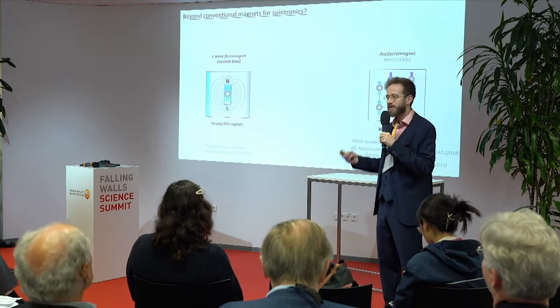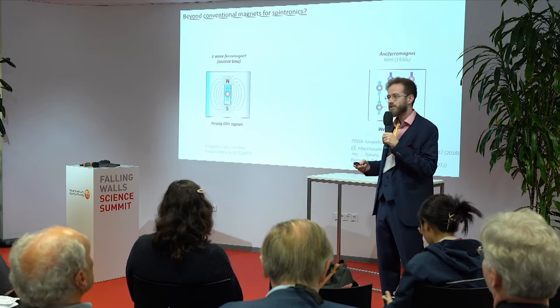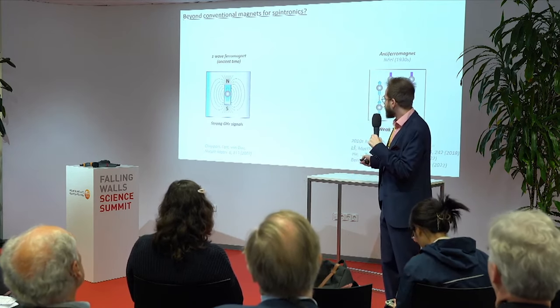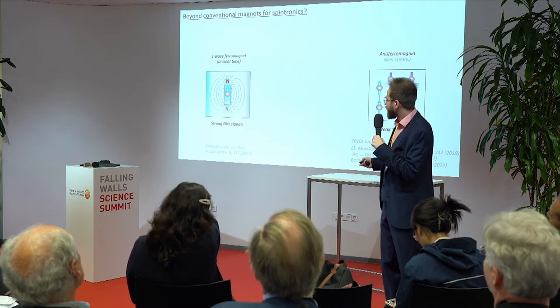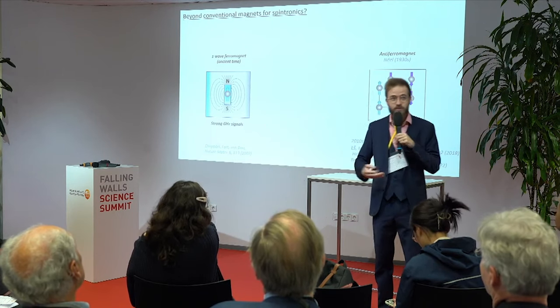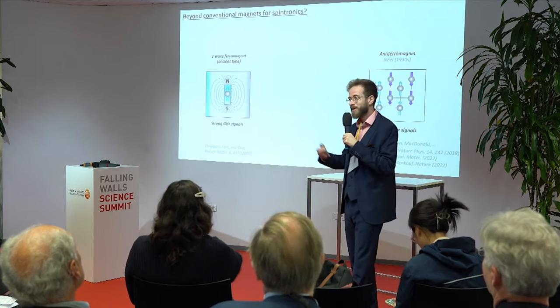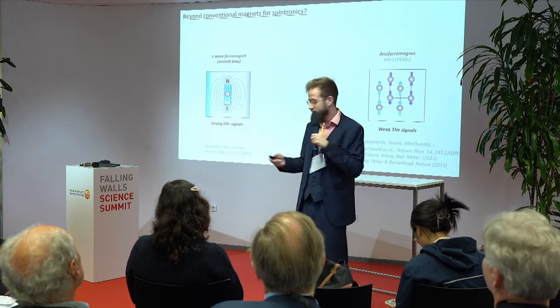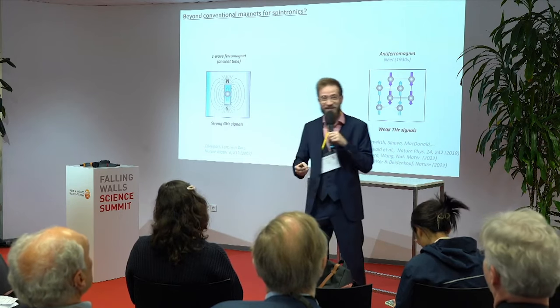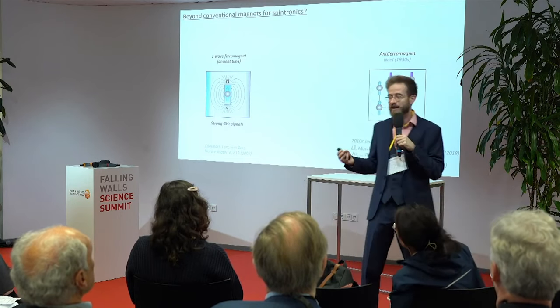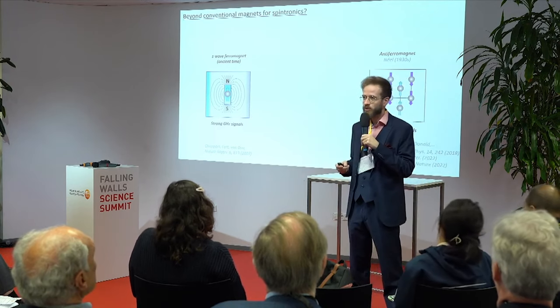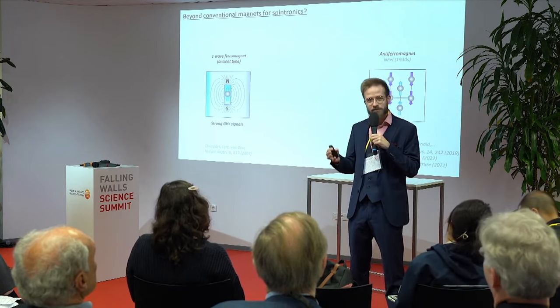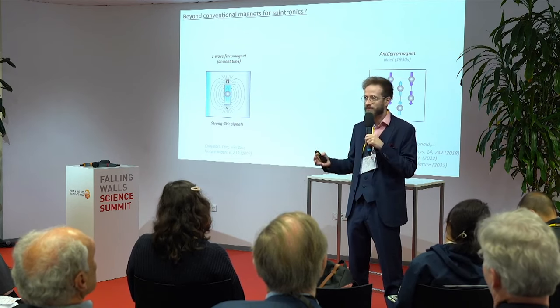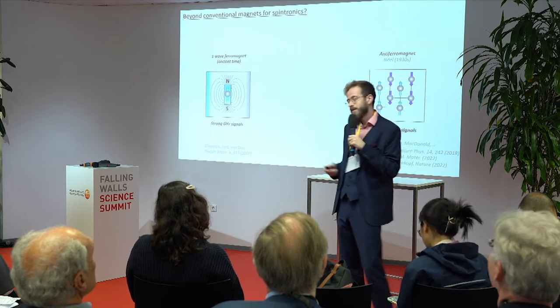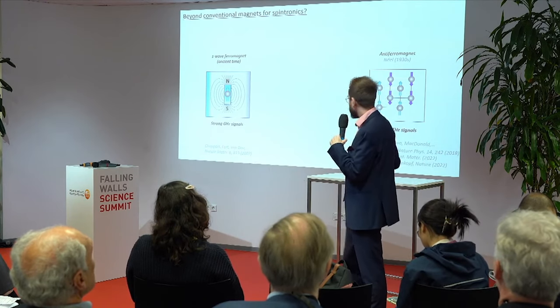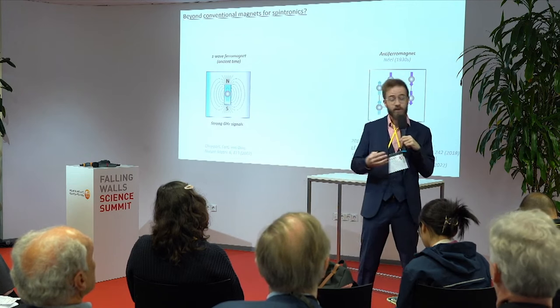So, these are the two conventional classes. Ferromagnets are characterized by magnetization, and since the end of the 19th century, thanks to Curie, we know that they can be thought of as pseudovectors. They have strong signals, however, they are limited to gigahertz frequency. So that's why, for instance, magnetic hard drives can go only as fast as gigahertz. On the other hand, antiferromagnets were discovered 90 years ago by Néel, and they have compensated magnetic order. So they do not have magnetization, and that's fantastic because we can switch them three orders of magnitude faster. However, at the same time, it's an obstacle because they are very difficult to read. The electronic signals are very weak in them.